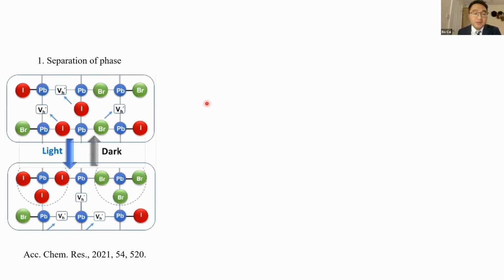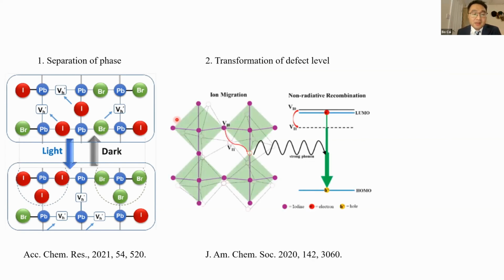As mentioned before, ion migration would bring negative effects on stability. First, experimental researchers usually use mixed halide perovskites to satisfy the bandgap requirements for high efficiency. Under illumination or an electric field, ion migration would induce phase separation, thereby leading to bandgap splitting and efficiency decay. Second, the ion migration process would give rise to the transformation of defect levels from shallow to deep. As we know, deep defect levels are harmful in optoelectronic devices because they convert energy from light or electricity to heat, therefore decreasing the conversion efficiency.